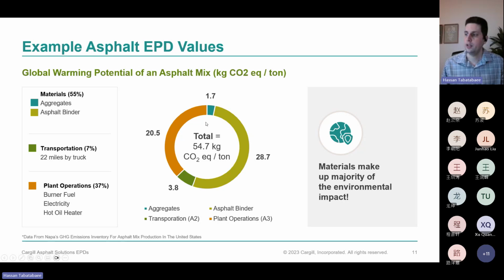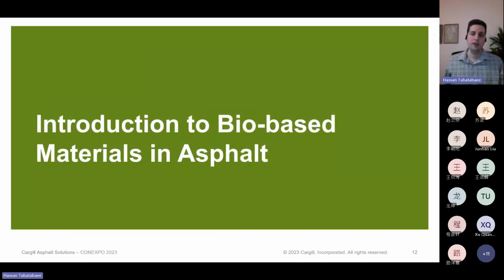This is followed by the energy that is spent on operating a plant and heating the aggregates and drying aggregates. So energy for heating and the asphalt binder production are the two biggest contributors to the carbon footprint of asphalt. And so when we look at reducing carbon footprint, those two aspects are definitely some of the ones to focus on significantly. So that's where the bio-based technologies come in and have started to be used.